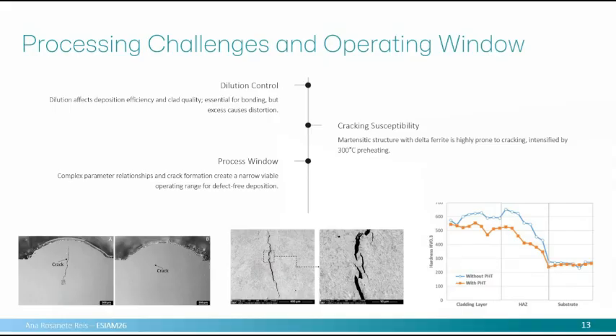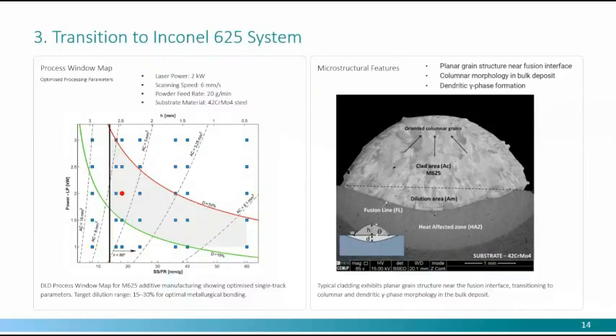You can see here the hardness that we got. This is the substrate. Of course, we get an improvement in hardness, but everything here has cracks. So we could not use this material directly in direct energy deposition. But the hardness was very promising. So we tried to go to Inconel.